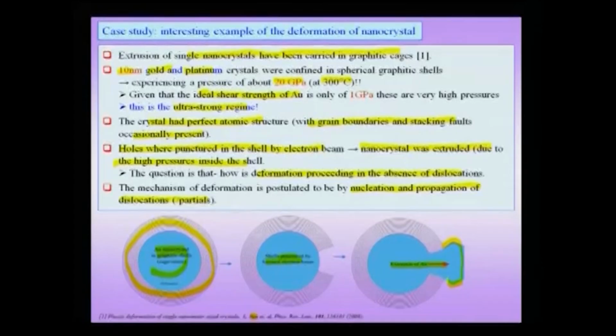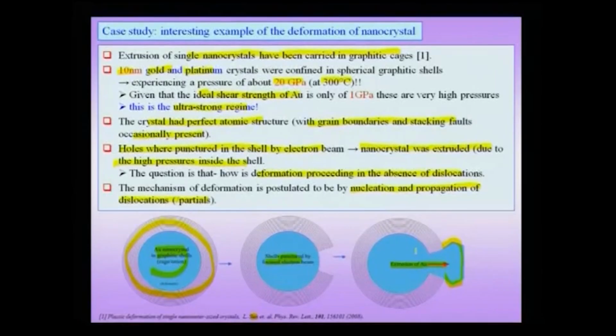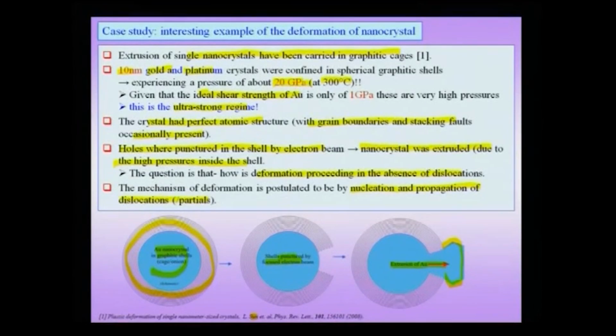effects could be actually smaller, but you do see that there is a faceting of the crystal when it comes out of the carbon nanotube, but this faceting cannot obviously take place without diffusion. So, that means diffusion is playing a role in the overall process, but they ruled out diffusion as a possible mechanism for this plastic deformation or the deformation of this gold nanocrystal through this punctured graphitic cage, and they propose that it is actually nucleation and propagation of partials or dislocations which is responsible for this kind of plastic deformation in the ultra strong regime of crystals, wherein this material is kept under a pressure of about 20 gigapascals. So, this is one nice example wherein a nanocrystal is placed inside a nano cage which is extruded by